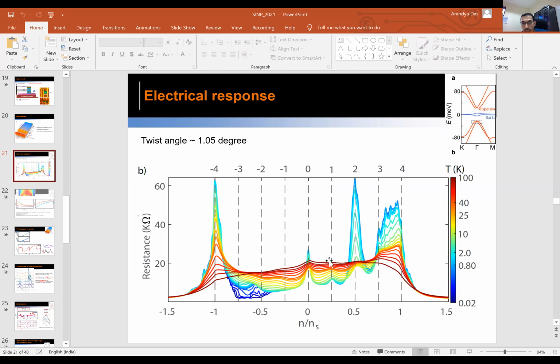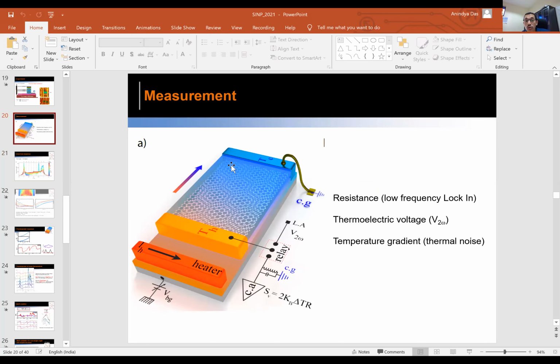But if you look at the flat band resistance, it is much bigger than that, like 10 kilo to 100 kilo. The point I'm making is that all these are two-probe, and this contact resistance is smaller than the channel resistance. The reason we choose the two-probe is the following. Because of thermal power, if you introduce other contacts, as we are discussing, the temperature profile will be modified. Once you put in a metal contact, the temperature profile is no longer linear, which is what we have assumed.